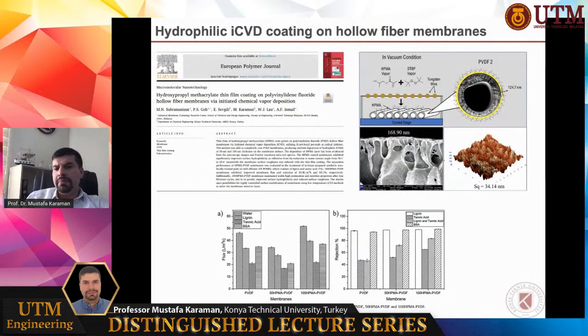Hydrophilic iCVD coatings on hollow fiber membranes. As I said before, we are collaborating with Amtech on some collaborative work on membrane science. Amtech is producing very good base membranes for us. We use such membranes as substrates to make their surfaces functional with desired functionalities to improve membrane performance. For example, in this study, we deposited hydroxypropyl methacrylate, a hydrophilic material, on top of polyvinylidene fluoride hollow fiber membranes. We were able to conformally coat the surfaces of those membrane materials, and as a result, we showed that permeation and rejection of water values improved very much after iCVD coating.